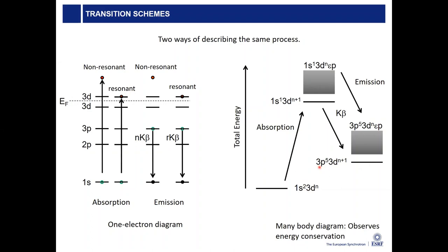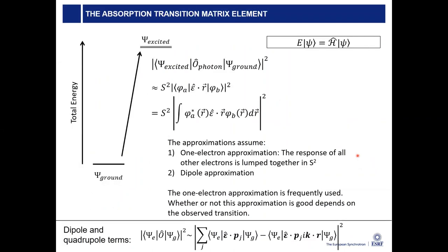This has many advantages because, as I said, it observes energy conservation, and it's a more useful way of describing your transitions, and it's easier to show the two-step process here. Okay, so how do we calculate this? Again, this is the total energy diagram. I go from the ground state to the excited state, and the energies of those states are calculated using the Schrödinger equation shown here, which is then put into some code, can be a DFT code or any code that gives you the energy of those states.